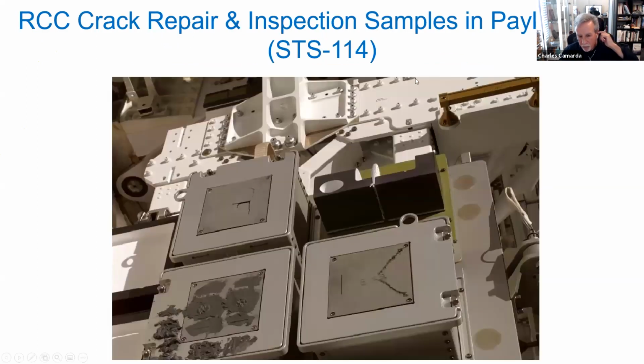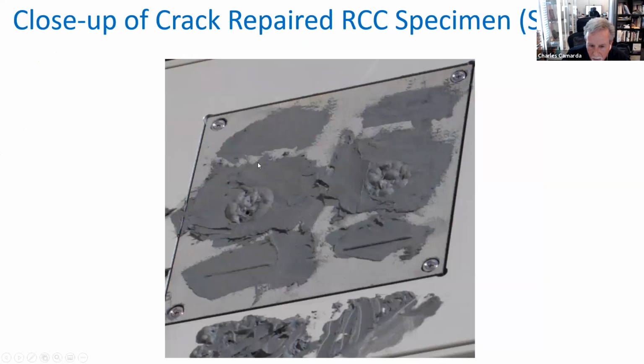And so what I want to show you here is that after Steve Robinson tried to create as good a repair as he possibly could on that damaged RCC material, that material expanded in orbit. It outgassed because we have a vacuum in space. So any elements of gas trapped in that material, when you put it in a vacuum, would expand. Now, we tested this in vacuum chambers on Earth, but space is a very large vacuum.